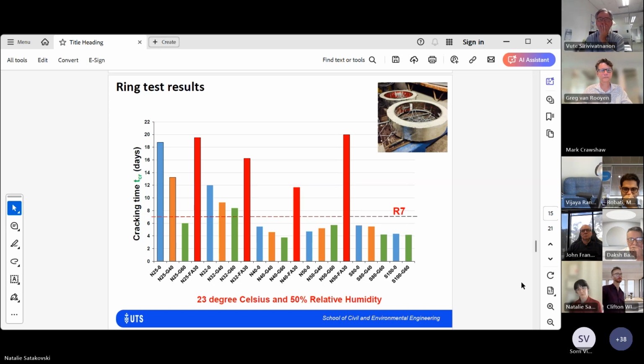Importantly, the concrete that are not cracking within the first 7 days are the ones performing better, but that doesn't mean they won't crack in the field. You have to keep in mind that the testing condition is a standard testing condition, 23 degrees and 50% relative humidity. If you don't include the water evaporation rate the day of the pour and a few days following the pour of the concrete, we're never going to be able to control early age cracking. That has to be part of the work of engineers, to consider case by case what's going to happen the day we're pouring the concrete. Next slide, please.